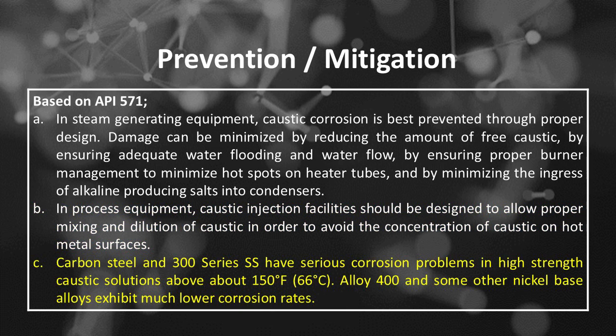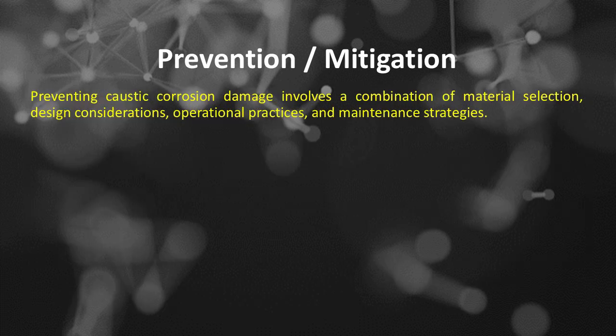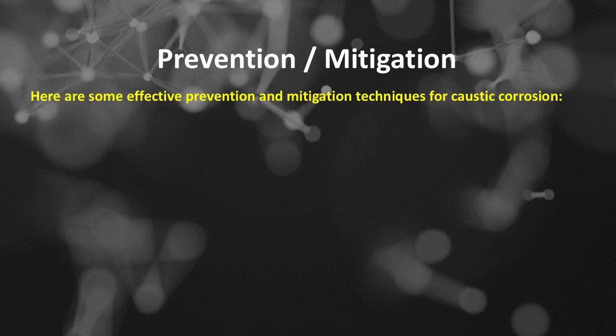Number C, carbon steel and 300 series SS have serious corrosion problems in high-strength caustic solutions above about 150 degrees Fahrenheit, 66 degrees Celsius. Alloy 400 and some other nickel-base alloys exhibit much lower corrosion rates. Preventing caustic corrosion damage involves a combination of material selection, design considerations, operational practices, and maintenance strategies. Here are some effective prevention and mitigation techniques for caustic corrosion.